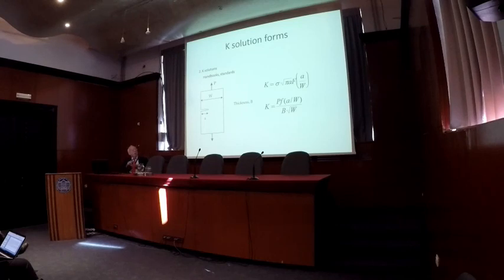They're the same, but two things. One is, if you have stress of a body, you have this kind of solution, which I call the capital F solution. So stress, square root of pi times crack length, and then this is a function of geometry and loading type. And in tests, usually this K solution is used, and that relates directly to the load. Now, if you would make the comparison between the two, you'd find out they're identical, but the little f in this one and the big F in that one are different.